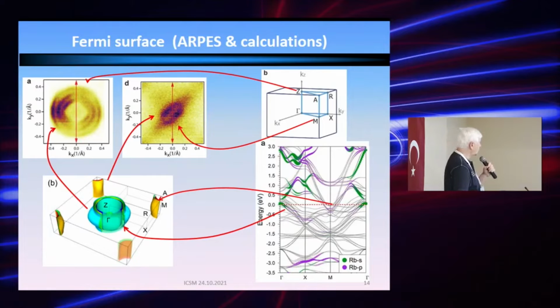Now we have to take a look at the calculations of the band structure, and we identify all these pieces of the Fermi surface with the electron bands and the hole bands. The hole bands are located in the center of the Brillouin zone, slightly deformed cylinders, and the electron bands are in the vicinity of the endpoint. So basically we conclude that the experiment and calculations are mainly in agreement with each other, without minor details which are not very important, and the total picture is similar to that specific for 122 materials. And so far at the Fermi level, I don't see any major difference with 122 materials.